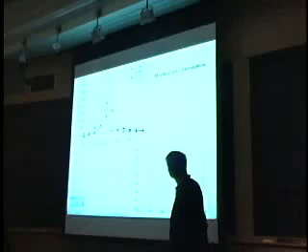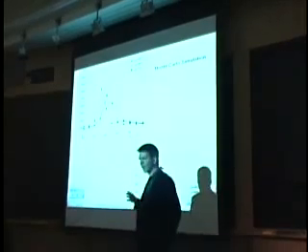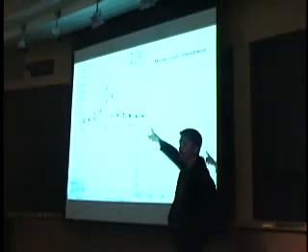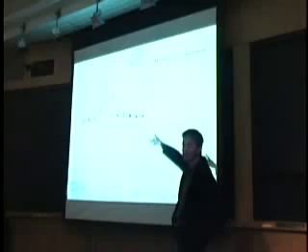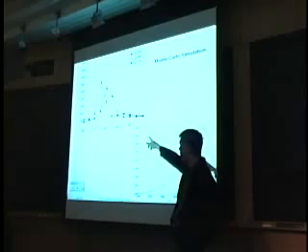It's maybe not refined enough to tell, but there's clearly a peak in the heat capacity. Let's say we take the green curve, which is at a particular oxygen chemical potential. There's a peak in the heat capacity. It's not very well defined. You shouldn't let yourself be misled: if you didn't draw the lines here, but just the points, that peak is essentially defined by 1 point, the green one. So you should always be careful, you may have very spurious behavior going on in one similar Monte Carlo situation.